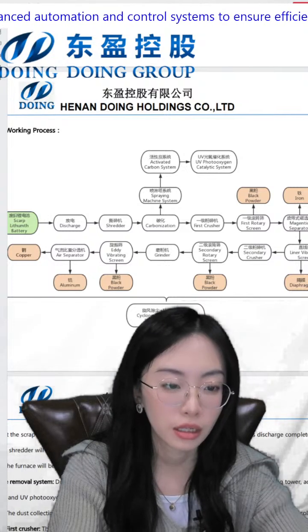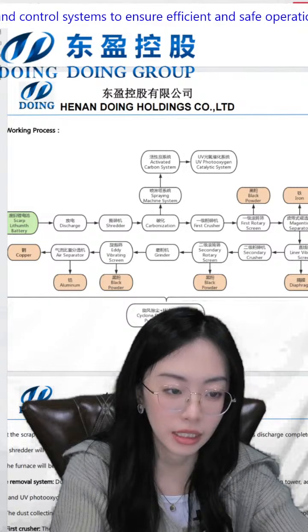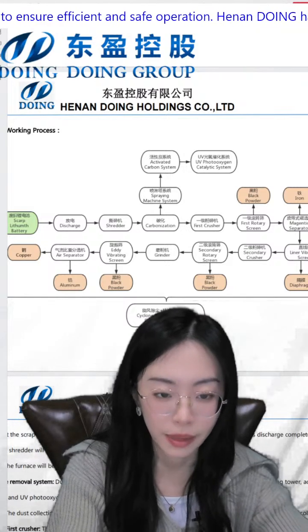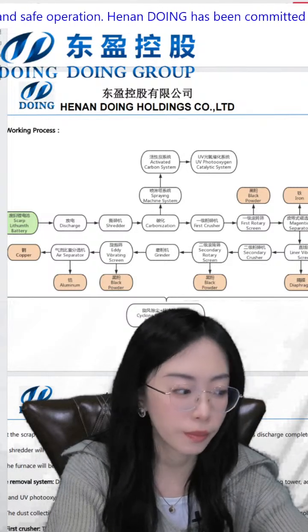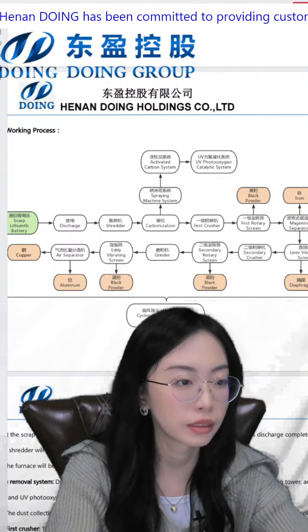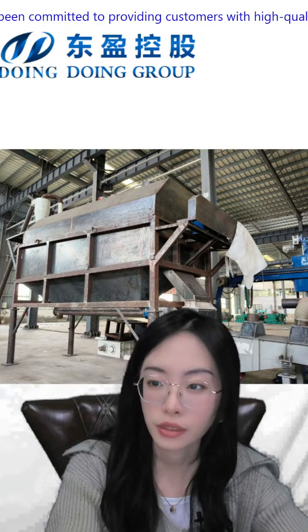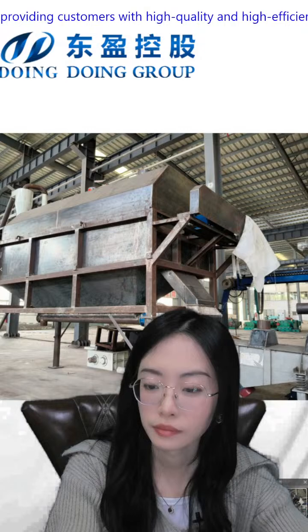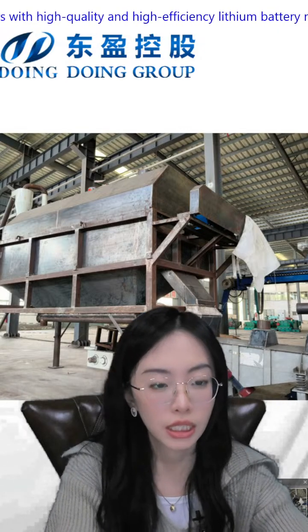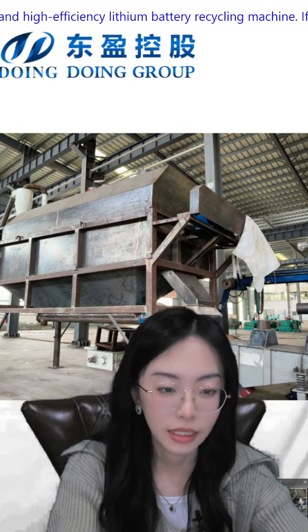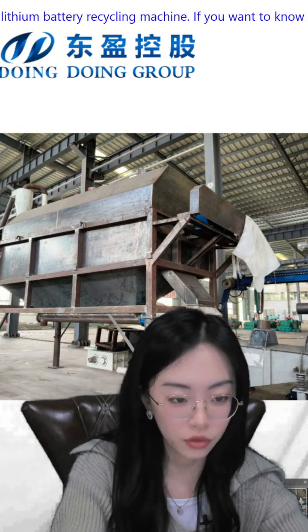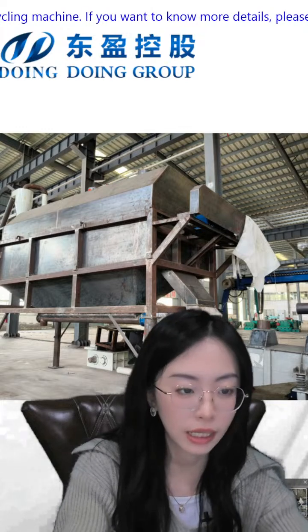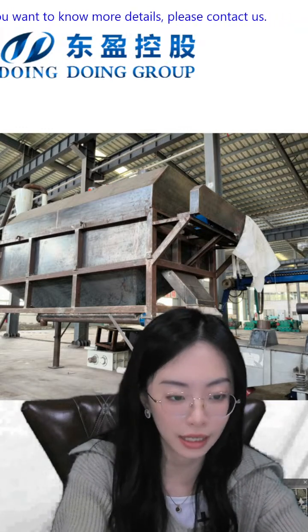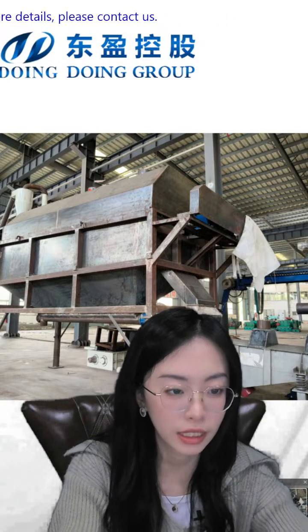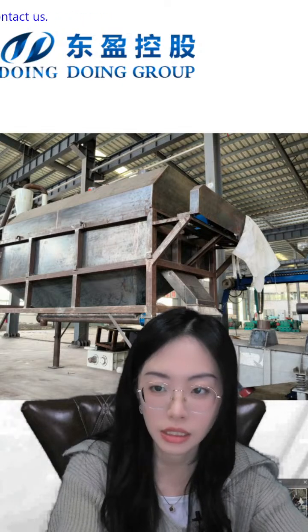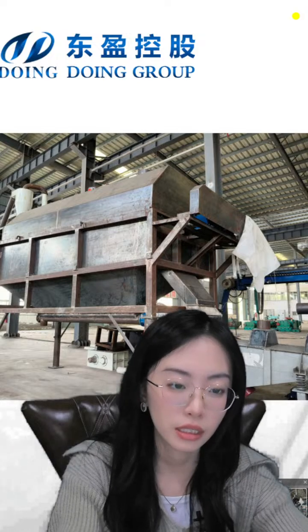We can completely volatilize the electrolyte in this lithium battery. So later I will show you some pictures of this lithium carbonization furnace. Here is what the furnace looks like. The furnace uses electric heating or gas heating. The heating temperature in this furnace is 100 to 450 degrees. So the electrolyte in this battery is completely volatilized in this furnace for harmless treatment. This is the step to volatilize the electrolyte.